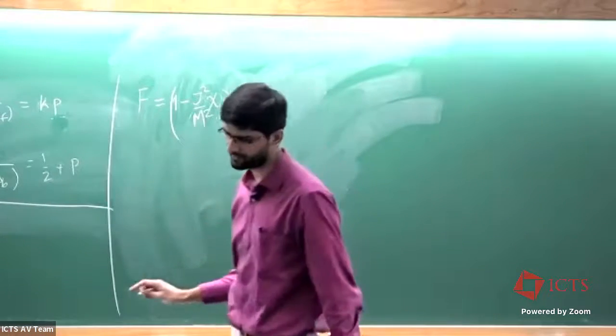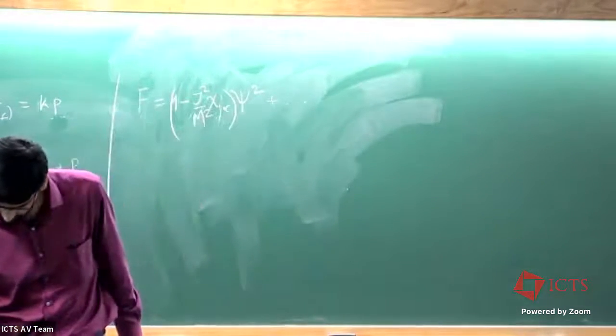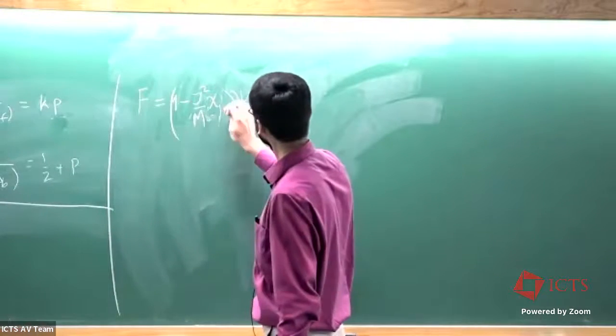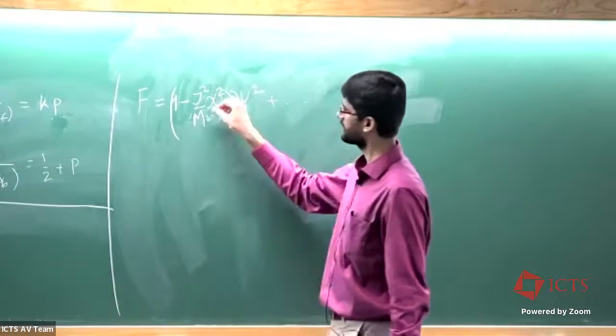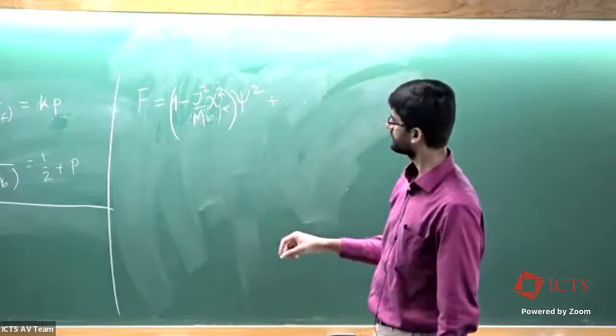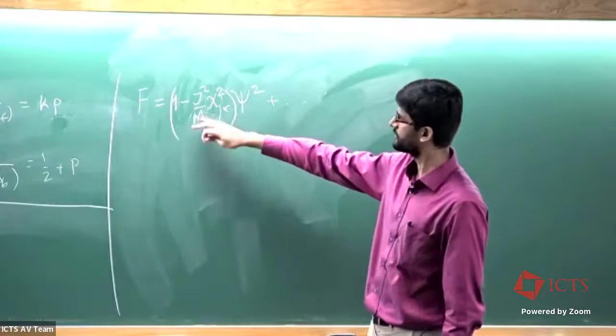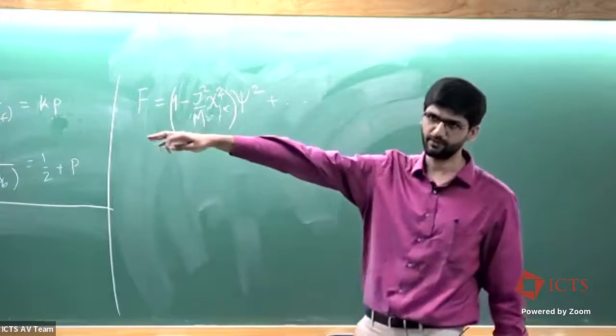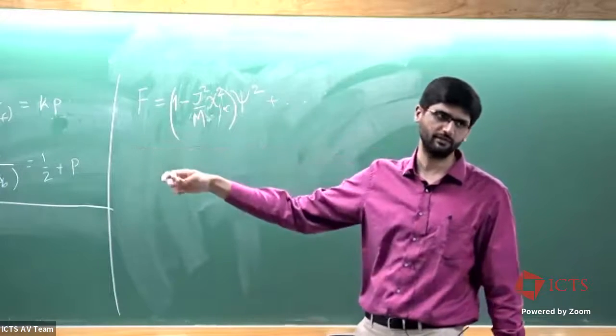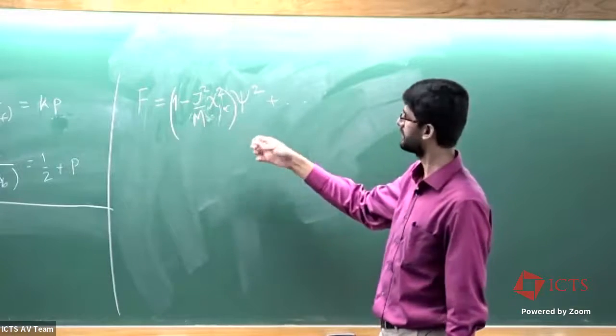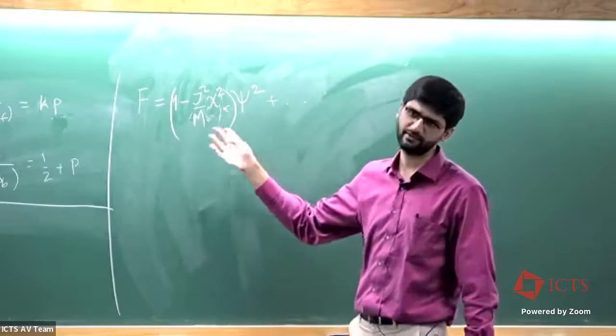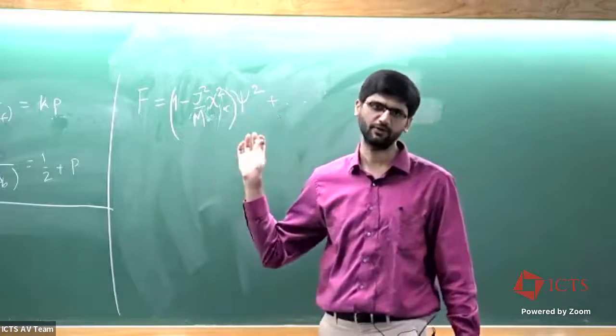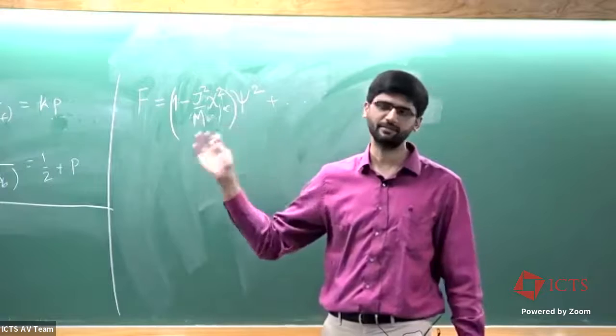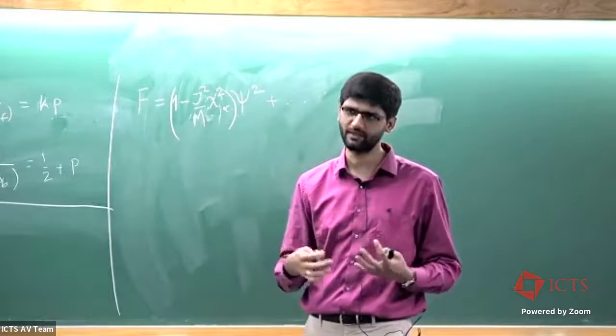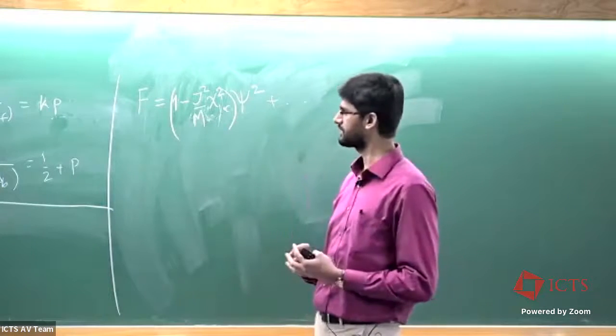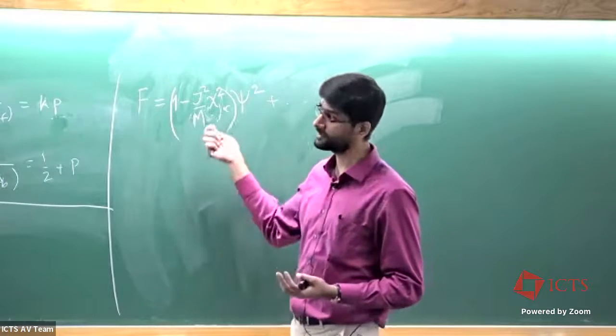Or it might be a square of that. I might be missing some factors. Oh, it's a square. Yeah, so it's j square chi local square over m. So now you can ask the question for this particular model, does it have an instability towards a spin glass phase by just looking at this simple Ginzburg-Landau kind of argument? It's not extremely precise, but it at least heuristically gives you an estimate whether there could be some spin glass instability. And it turns out it does.